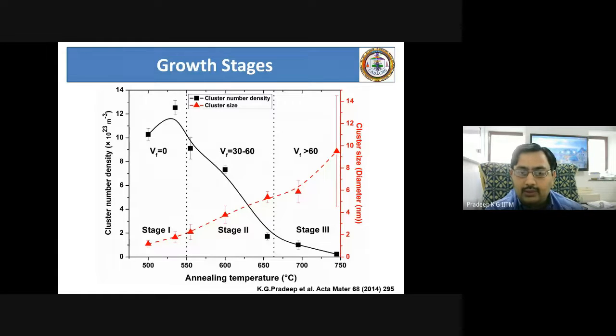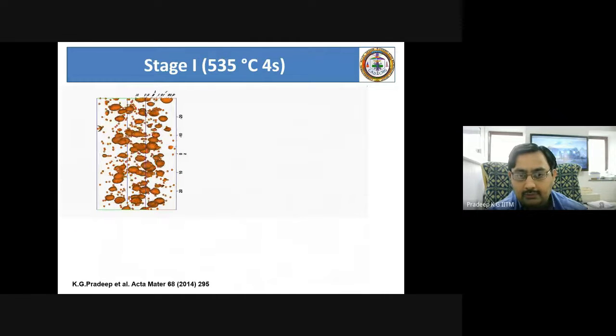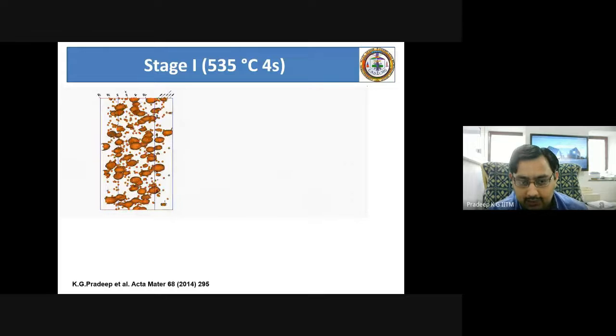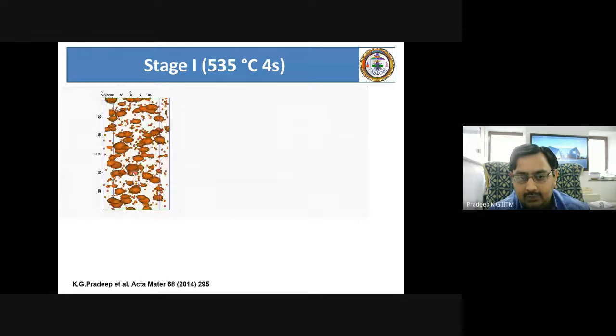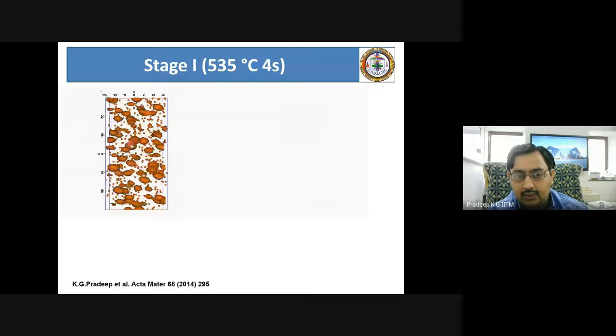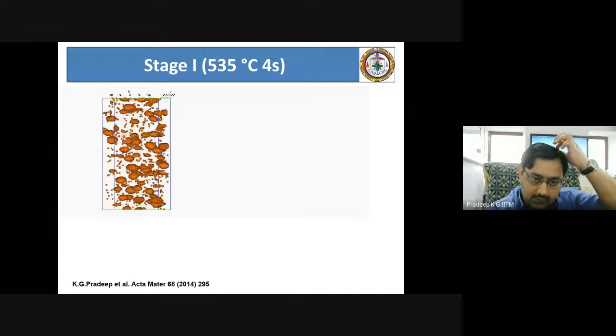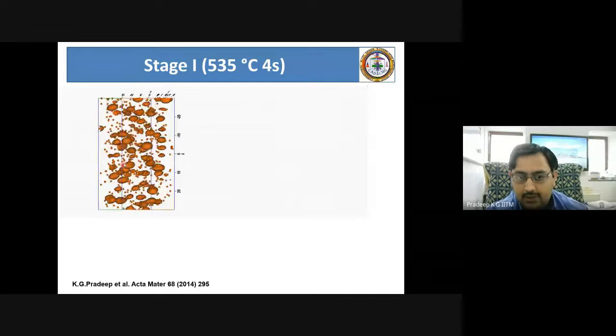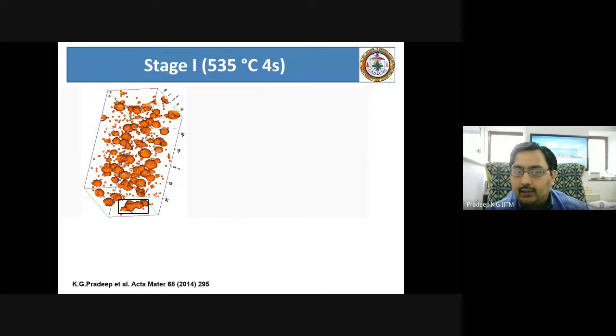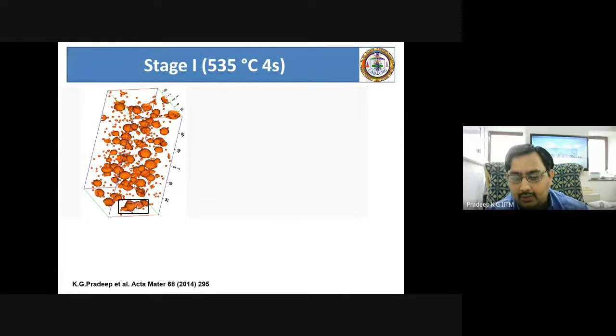Now, if you want to understand what their mechanism of growth is and what the crystallographic nature of these clusters that have emerged from a completely amorphous state is, then we can further go into the atom probe data, look at these atoms in 3 dimensions, and you can see where cluster regions are all identified with this kind of isoconcentration surface, but individual copper atoms are spread everywhere. Then you can even zoom in and see there are certain locations where individual copper clusters are in contact with each other, and there are locations where they are isolated.